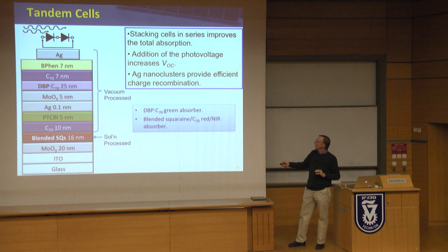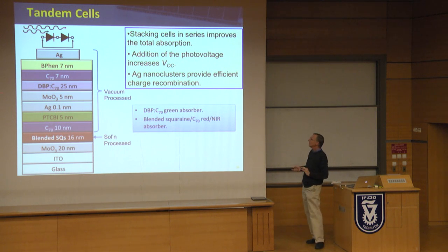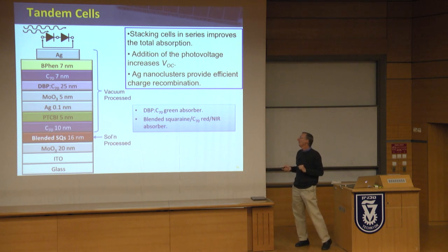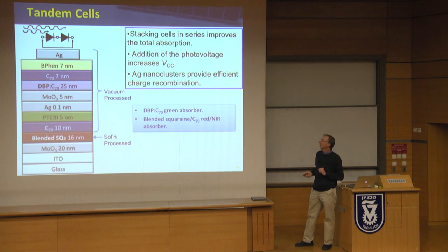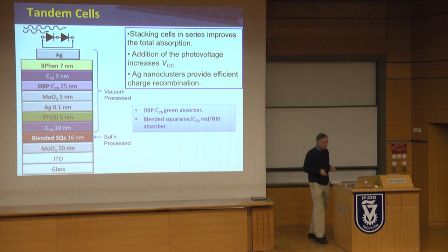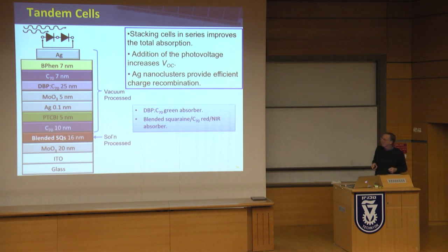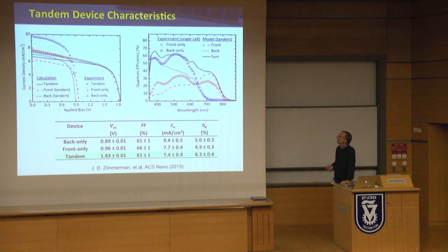And so now you have a negatively charged silver particle. A hole from this side comes in, and it sees the negatively charged nanoparticle, and it then recombines there. So you got to get rid of those internal charges. And the silver, just a whiff of it, gives you an extraordinary efficiency for doing that. The nice thing about this is it has 2 cells, and they're in series, so you get twice the voltage. And everybody knows that you need more voltage than current if you want to have high efficiency. So these give you high voltage, good current, and they're pretty simple to make.